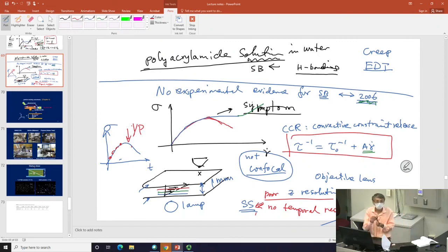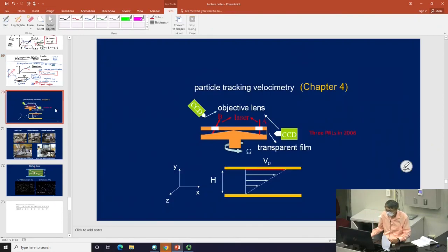not so much that you can tilt your microscope 90 degrees, but rather you can have an objective lens through an adapter directly connected to a CCD camera. So I can have my observation lens pointing at any angle I wish, right? Including horizontally. So looking at it horizontally, of course, means you see every layer at the same time. You look into that gap directly. You see every layer at the same time.